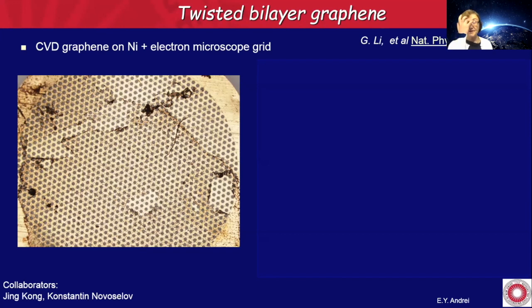So here is the first experiment that we did, and here is where serendipity came into the picture. We were trying to measure the properties of a single graphene layer that was isolated from the substrate, because the substrate introduces a lot of disorder. At the time, we didn't know how to handle these samples. This sample was grown by Jing Kong at MIT, using chemical vapor deposition of graphene on nickel. It was then sent to Manchester to Kostya Novoselov, who deposited it on this electron microscope grid.